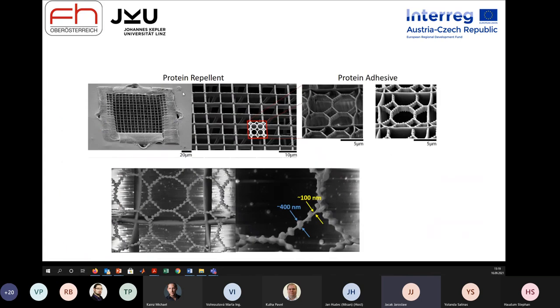So when we look closer into the structures, we see nicely that these are 3D features. We have a different periodicity on top. Then we have connectors here and a different periodicity below. Why is it so? On top, we wanted the cells simply to grow on top of this grid, and the second cell should enter the holes, and so the holes on the back were bigger, and so they were able to enter and interact with the other cells.